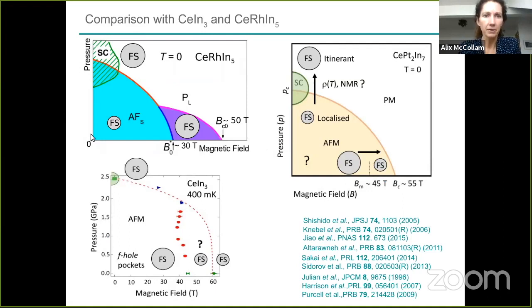So this again is the pressure versus magnetic field phase diagram of cerium rhodium indium 5. And I've just sketched on here what we believe to be the size of the Fermi surface. And when I say the size of the Fermi surface, I mean whether the f-electron is in the Fermi surface, or whether it's hybridized with the conduction electrons and itinerant, or at least partially itinerant. So this would be the large Fermi surface, which is represented by a large gray circle, or whether the f-electron is localized, and this is the small Fermi surface, represented by a small gray circle.